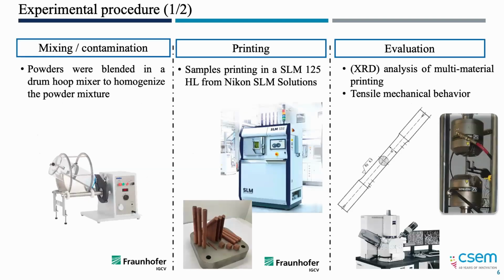So the strategy that we actually went through is, first of all, a mixing of the powders with specific ratios. I will come to that in the next slide. The parts were 3D printed with an SLM Solutions machine at Fraunhofer, and of course there is the evaluation with XRD, SEM, and tensile testing.